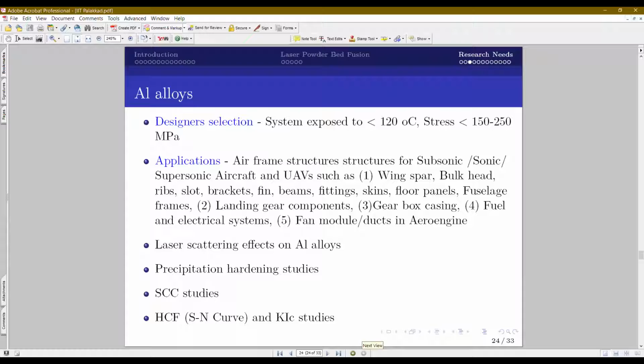Second is precipitation hardening. Aluminum alloys are strengthened with precipitation hardening. But 3D printed alloy is already in a quenched state. Do I need solution treatment again, or can I directly go for aging? There are some studies which show that T5 treatments are better than T6 treatments. So still a lot more can be done in the precipitation hardening heat treatment area for 3D printed aluminum alloys.